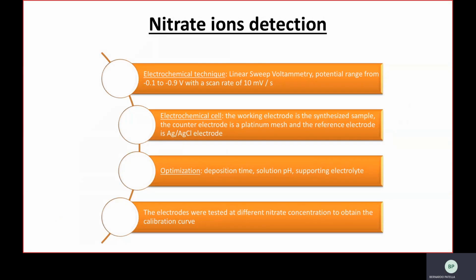In order to use the as-prepared electrode as an electrochemical sensor of nitrate, linear sweep voltammetry was selected as technique, using a platinum mesh as counter electrode and a silver chloride as reference electrode. The sensing platform was optimized in terms of deposition time, solution pH, and supporting electrolyte.